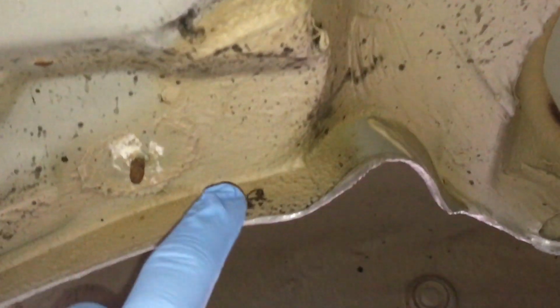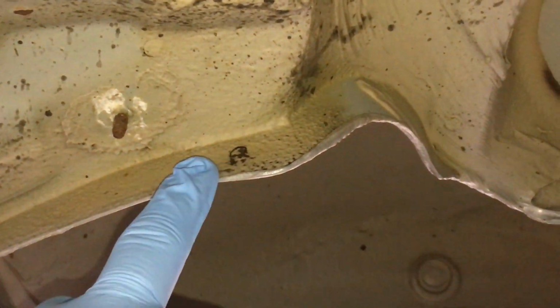For instance, when this car came in, it didn't have any cleaning, so we didn't even notice that crack until we cleaned a small section, and then we could see that there was a crack next to the left rear mounting point, which is now quite visible. A couple of spot welds that have moved. A spot weld here which is definitely broken. The other one might be okay underneath that seam sealer. We'll see more once we take that off.